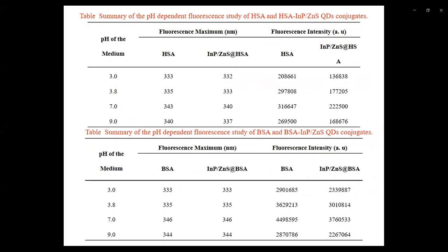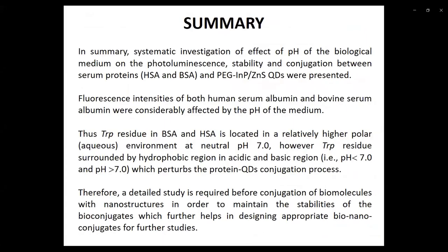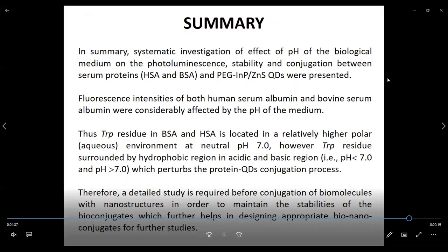As I already said, there is a red shift in the peak position for pH 3 to 7 and a blue shift in the peak position for pH 7 to 9 for both the proteins and conjugates. In brief, the overall summary is listed here. Quantum dots have shown higher stability and more fluorescence intensity at the pH of 7 to 9. HSA, BSA, and their conjugates with the QDs also showed more stability in the pH region 7 to 9.